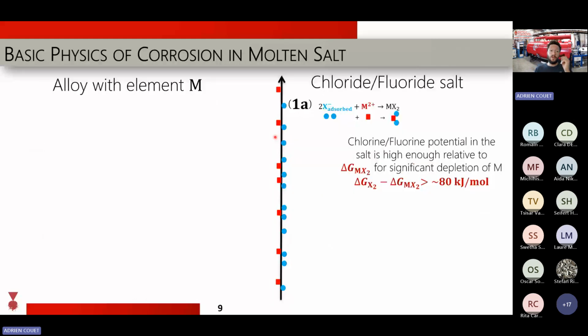All right, so let's take a look at the molten salt a little bit more closely, on how materials corrode in molten salt. Well, it's a thermodynamic process first, so you need some driving force for this to happen. For the corrosion to happen, you need to look at two main physical quantities. One is the partial pressure of your halide salt, so that is fluorine or chlorine. I put X here, it could be fluorine or chlorine, doesn't really matter. If this partial pressure of fluorine or chlorine in your salt is larger than the free energy of formation of your metal chloride or your metal fluoride by a few tens of kilojoules per mole, then you will have this driving force that will lead to corrosion of your material.